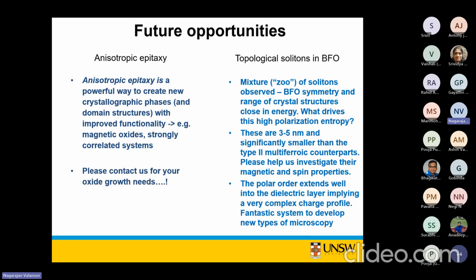Okay, so it's slightly bismuth deficient, so it's p-type. Yes, we enrich the target by at least 20%. Have you seen any dependence on the effect of fluence? By changing the fluence, you can also get a very low growth rate. But it's not just the fluence. I don't have a physics answer. I have an anecdotal answer. It's also what happens in the travel time with the energy of the plume.